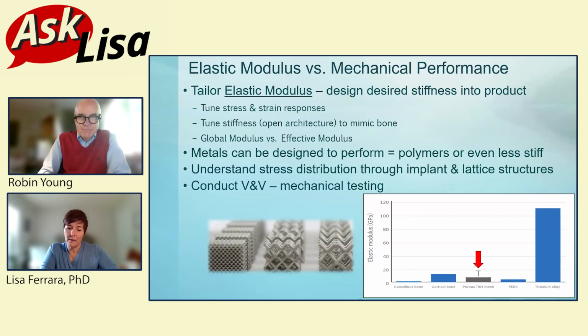And what folks weren't understanding is that's the bulk material. It has a high elastic modulus, meaning it's very stiff, of a cube of solid titanium. But we're not dealing with cubes of metal anymore. We're taking that metal, we're building structures. So now we're looking at what we call the effective modulus of the structure. And that structure can be programmed, can be tuned to have very different moduli. Even within one implant, you can have regions of different moduli, which is the beauty behind it.